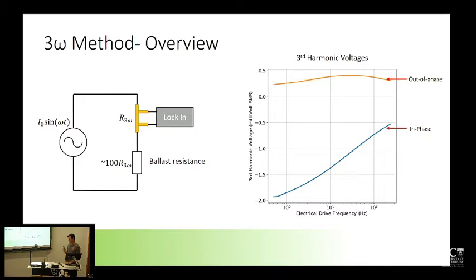And the thermal penetration depth of some AC temperature wave or heat wave penetrating into the material is inversely proportional to the frequency with which you're driving. The units of power are joules per second. So there's the second relationship. If you're driving it faster, you're going to get less of a temperature response out of the system. So you can see how if you start increasing the frequency, you're going to be measuring less of a depth into the material. And so your in-phase response has this curve down as you're penetrating less deep into the material. And you can relate the slope of this in-phase temperature response directly to the thermal conductivity, which is the basis of this whole experiment.